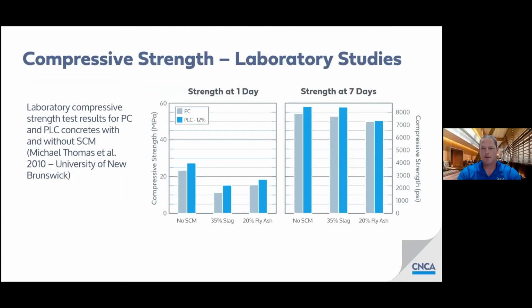I'm only going to put up a few graphs where I compare Portland limestone cement to ordinary Portland cement. What we've got here is some laboratory research that was done by Dr. Michael Thomas at the University of New Brunswick in Fredericton, Canada. He compared strengths at 1, 7, 28, and 56 days. Portland cements, which are in kind of the lighter gray bars, Portland limestone cements, you'll see that 12% on the graph there. This Portland Limestone Cement happens to have 12% limestone. And the strengths with no supplementary cementitious materials, a 35% slag mix, and a 20% fly ash mix.